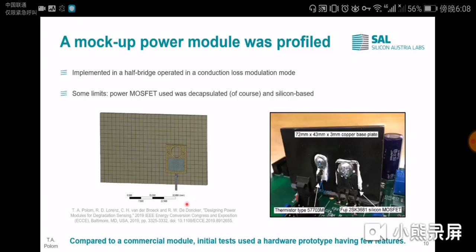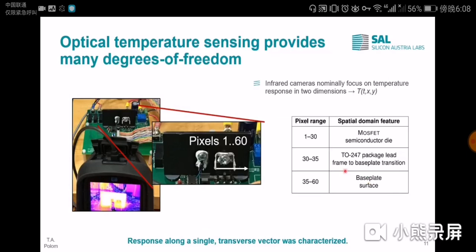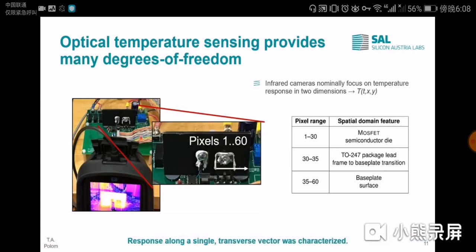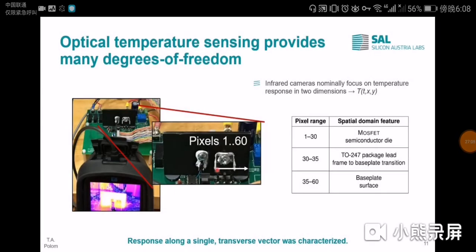Compared to a commercial module, these initial tests of thermal frequency response measurements used a hardware prototype having just a few features that we could control in the lab. I mentioned that we used optical temperature sensing in order to monitor the thermal response as losses were dissipated harmonically in the MOSFET chip. And to be specific, we monitored the response along one of the two available vectors. So we looked in the transverse direction as the power MOSFET was dissipating conduction losses.